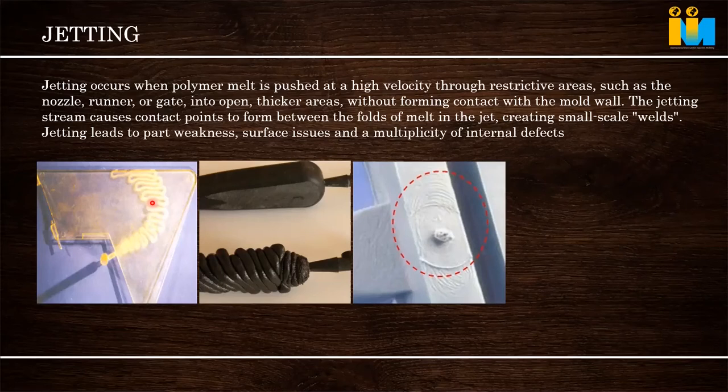Mold temperature and proper melt temperature also help optimize this problem. We assume that with yesterday's training, everything, mold temperature, melt temperature, pressure, is kept as per 98% injection, then holding, all done. After that, if this problem comes, then we have to take care of the gate thickness, then give some projection so that the restriction happens and the melt will not shoot. Sometimes providing a cold slug well near the gate also diverts the melt suddenly. These are the tricks to solve this problem.